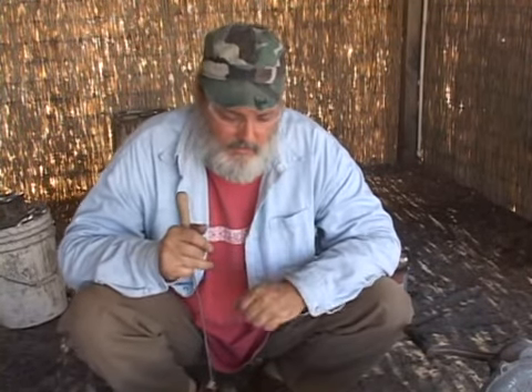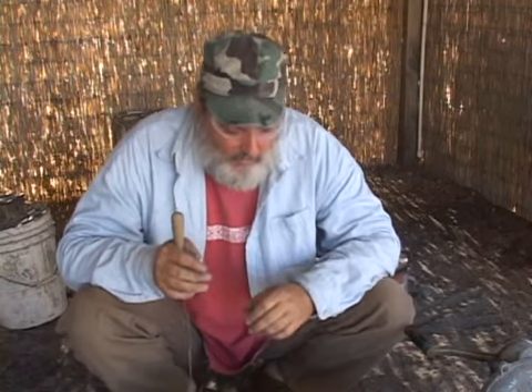If the edge rolled, the temper is too soft. If it chipped out, the temper is too hard. So you want to get it somewhere in the middle where it won't roll and it won't chip. With this 5160 steel, I have found that about a bronze colored edge works about the best for me. So that's what I'm going for, but experiment on your own and see what you like. Different steels will perform in different ways, so you might want to use a different temper on 01 tool steel than you would on 5160.